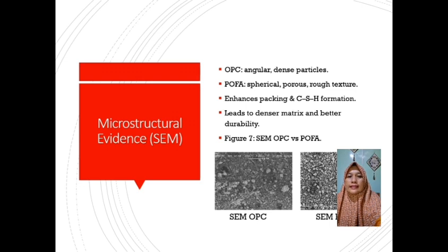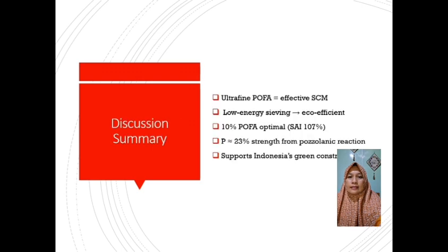The summary of this paper is that ultrafine sieved POFA is an effective SCM. Low energy, saving, enhanced eco-efficiency compared to grinding. 10% POFA shows the best mechanical and environmental balance with a strength activity index of 107%. Pozzolanic contribution accounts for approximately 23% of total strength. And the material supports Indonesia's green construction agenda toward carbon reduction.